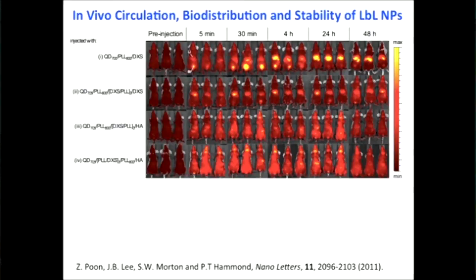If we just have this one bilayer on the quantum dot in dextran sulfate, we found with a tail vein injection, here's our mouse, look where it's lit up. In 5 minutes, the bladder lights up. Okay, we're losing poly-L-lysine. And over 30 minutes, the bladder lights up multiple times. We're losing this material. Yeah, the body's getting rid of it. It's falling apart. And we found that out because in a similar vein, we looked at where the quantum dot is. The quantum dot does not track with the poly-L-lysine. It hangs around a little longer, comes out at a different time. So this whole thing is sort of falling apart.